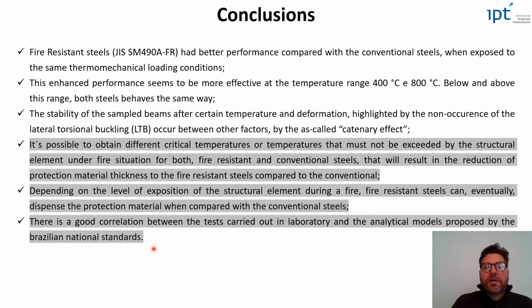As I said, these gray conclusions here are related to the analytical phase of my work. It is possible to obtain different critical temperatures, or temperatures that must not be exceeded by the structural element in a fire situation, for both fire-resistant and conventional steels. That will result in a reduction of the protection material thickness for the fire-resistant steels compared to the conventional. Depending on the level of exposure of the structural element during the fire, fire-resistant steels can eventually dispense with the protection material when compared with the conventional steels.